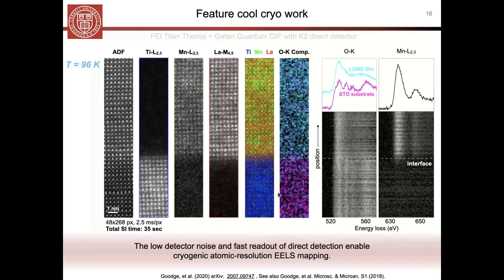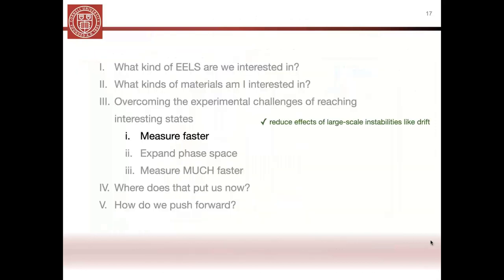This data is high enough quality that, for example, again, looking at the oxygen K edge, which contains a lot of rich information about the bonding in these materials, we can very easily map this evolution from the substrate to the interface, and we can look at the fine structure of some of the other core loss edges as well. And so this is very promising for starting to extend both the elemental but also the chemical mapping that we're really interested in, out to two dimensions under these kind of in situ conditions.